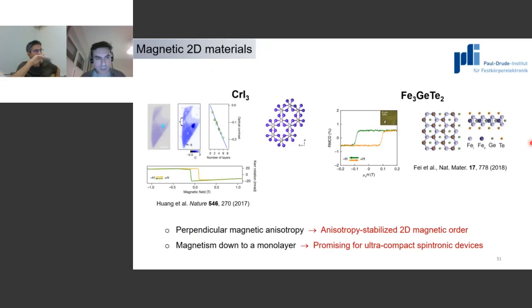But what people observed, I think in 2017, when the first paper came, for chromium iodide flakes exfoliated from bulk crystals, as well as one year later for iron germanium telluride, is that even monolayer-thick flakes would show magnetic order if you perform, for instance, Kerr rotation measurements, so-called MOKE measurements, and they see this ferromagnetic order, which is believed to be related to the fact that these flakes have a very strong perpendicular magnetic anisotropy. That means the spins are aligned out of plane,